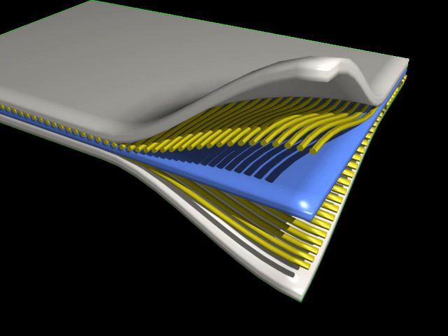Failure. Shock, impact, or repeated cyclic stresses can cause the laminate to separate at the interface between two layers, a condition known as delamination. Individual fibers can separate from the matrix, e.g. fiber pullout. Composites can fail on the microscopic or macroscopic scale. Compression failures can occur at both the macro scale or at each individual reinforcing fiber in compression buckling. Tension failures can be net section failures of the part or degradation of the composite at a microscopic scale where one or more of the layers in the composite fail in tension of the matrix or failure of the bond between the matrix and fibers.